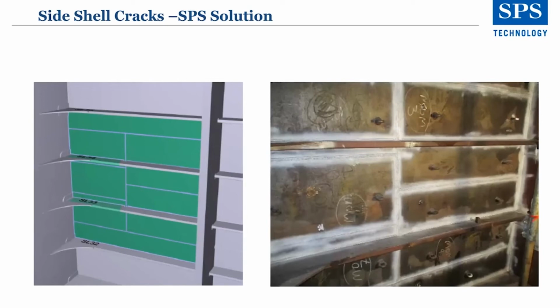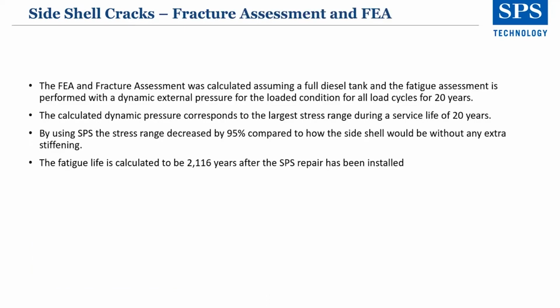SPS polyurethane then is injected from the bottom of the cavity and fills the space between the new plates that are in position and the hull where the cracks have formed. Why was SPS chosen? And what was it chosen for? SPS was chosen to strengthen the area so the cracks wouldn't grow.